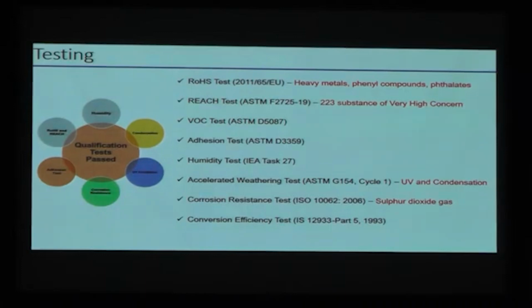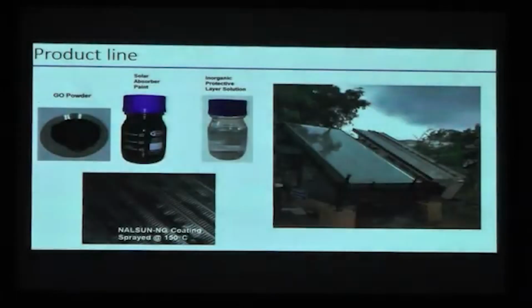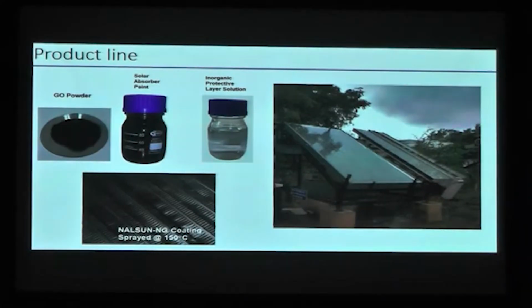And the corrosion resistance test, which mainly uses sulfur dioxide gas, this test facility is not available in the country. So for this test, we sent the samples to TUV Rheinland, Germany, and the coating has qualified this test. The major test is the conversion efficiency test. The conversion efficiency test is nothing but how much our coating is absorbing the solar energy and converting it into thermal energy. To do this test, we prepared a solar water heater panel with the help of private industries, and this panel was sent to the Regional Solar Energy Testing Center, Madurai, and they tested this coating for almost 2 months and provided a certificate.